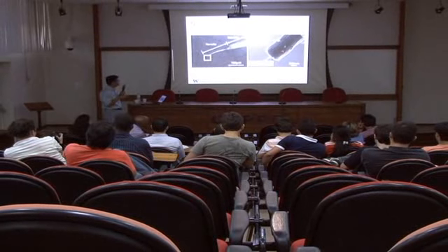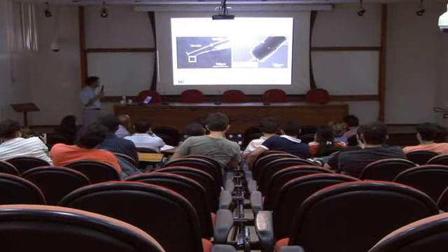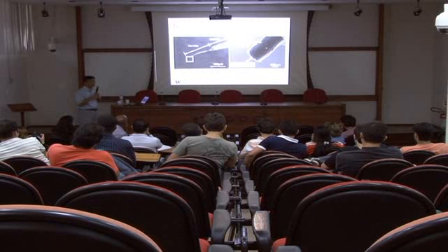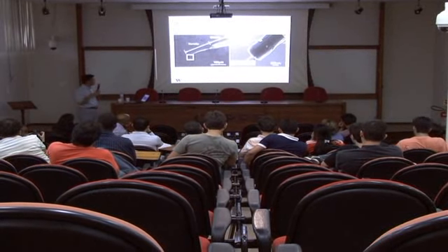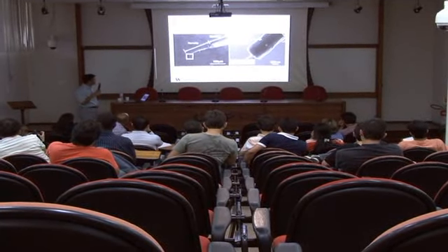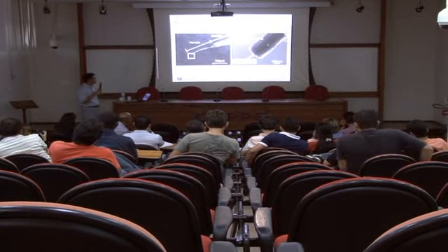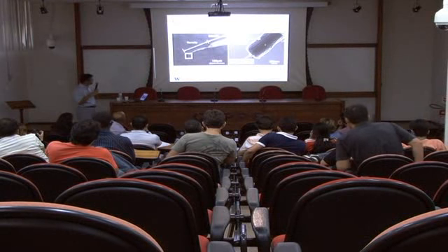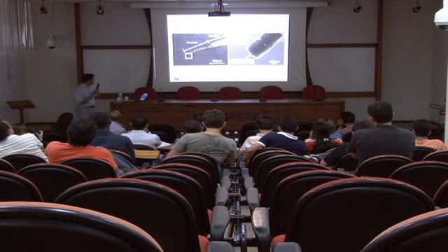The diameter is about 500 nanometer, and it's coated with single-walled carbon nanotubes in order to make these silicon carbide nanowires electrically conductive. So we have these branched dendritic structures, and at the tip end, we can concentrate the particles. Of course, the electric field will be generated on the dendritic structures. So particles also will be attracted around that range.